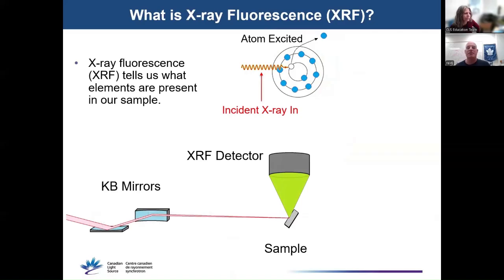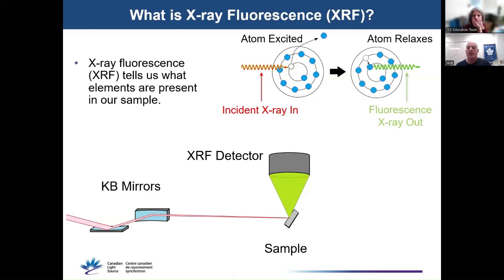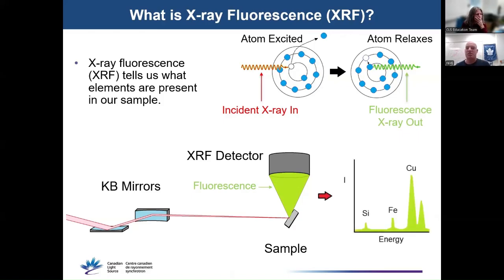An experiment typically looks something like this. We use mirrors called KB mirrors to focus the incident X-ray beam down to a very small spot on the sample. When the X-rays hit the sample, they excite atoms in the sample by knocking an electron out of the atom. This excited atom is not stable, and as the atom relaxes, it emits a new X-ray. This is called X-ray fluorescence. We use a detector to detect the fluorescent X-rays, and the X-rays from different elements will have different energies, so we can tell them apart. So this cartoon XRF spectrum at the bottom right here has peaks from 3 different elements: silicon, iron, and copper. But they all have different energies, and so they can all be readily identified.